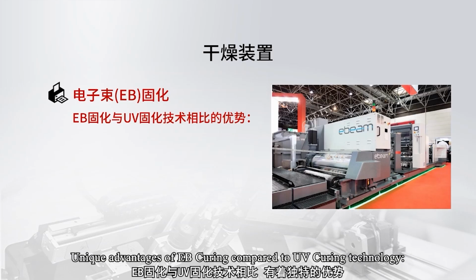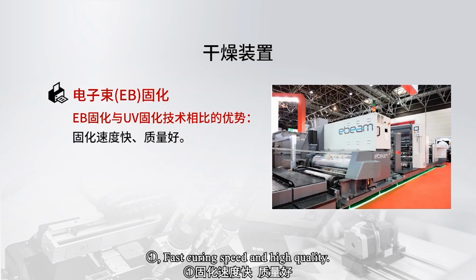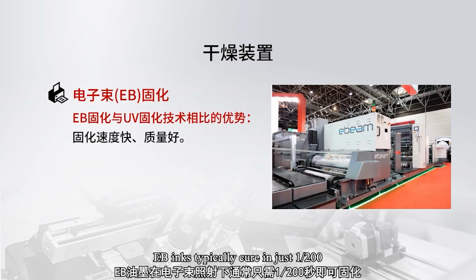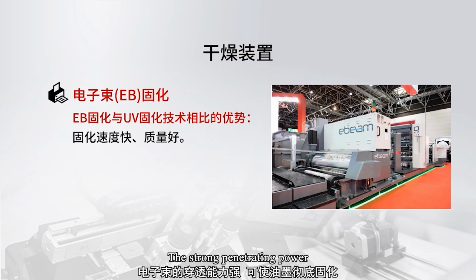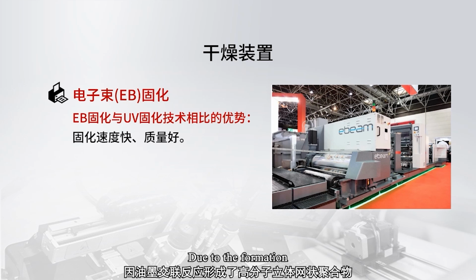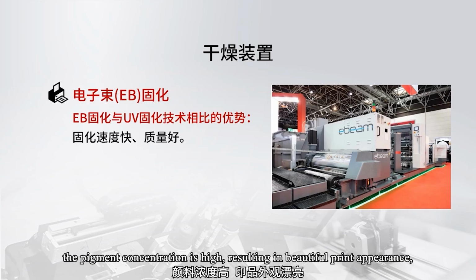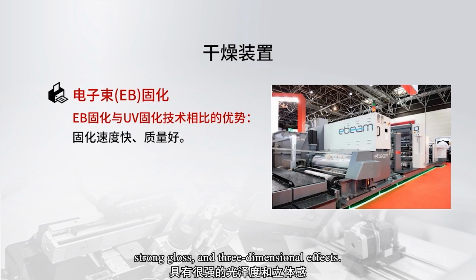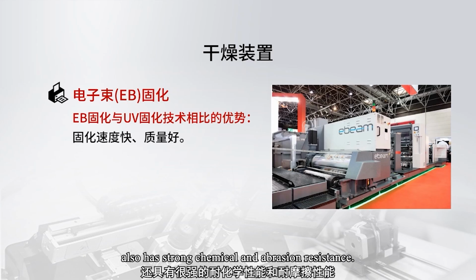Unique advantages of EB curing compared to UV curing technology. 1. Fast curing speed and high quality. EB inks typically cure in just 1/200th of a second under electron beam irradiation. The strong penetrating power of electron beams ensures thorough curing of the ink, due to the formation of high molecular three-dimensional network polymers through ink cross-linking reactions. The pigment concentration is high, resulting in beautiful print appearance, strong gloss, and three-dimensional effects. The ink film surface also has strong chemical and abrasion resistance.